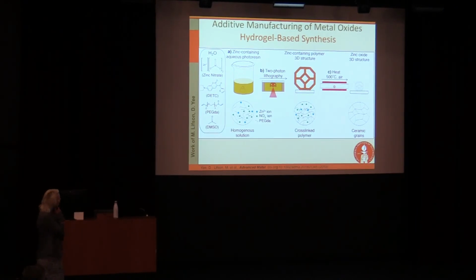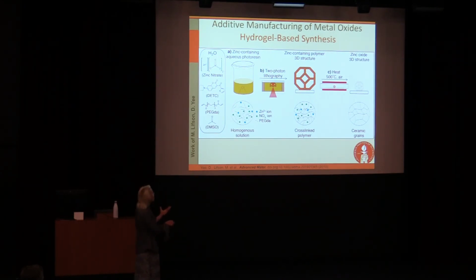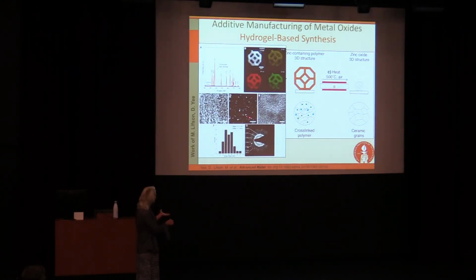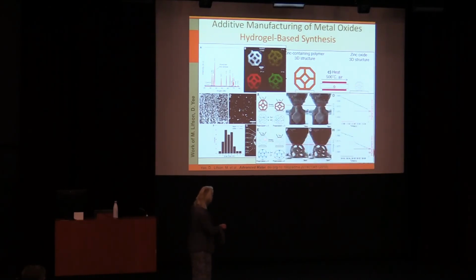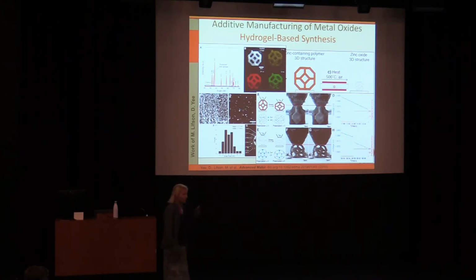Now for metals, we're moving on to metal oxides, and my student Daryl figured out that you can do hydrogel-based synthesis, so no more acrylic stuff. This is actually all water-based, all aqueous, and you can use metal salts. This is a way to make zinc oxide, for example, using this hydrogel-based synthesis. And legitimately, zinc oxide, and what do we know about zinc oxide? What are the most prominent properties of zinc oxide? Piezoelectric, right? Here's what we discovered: when you compress it, this is the zinc oxide part, it undergoes a voltage drop. So it preserves its piezoelectricity, and here's the unexpected part. If you look, those of you who speak TEM, if you look at this, it's very, very nanocrystalline.